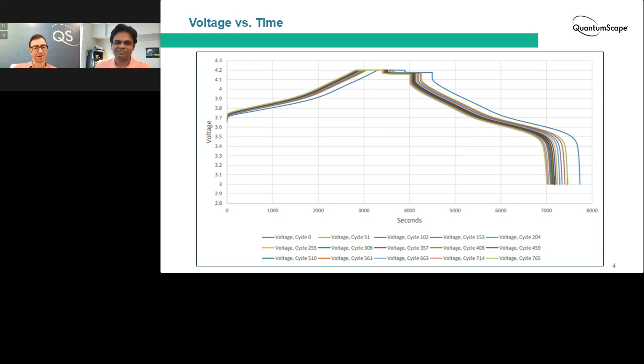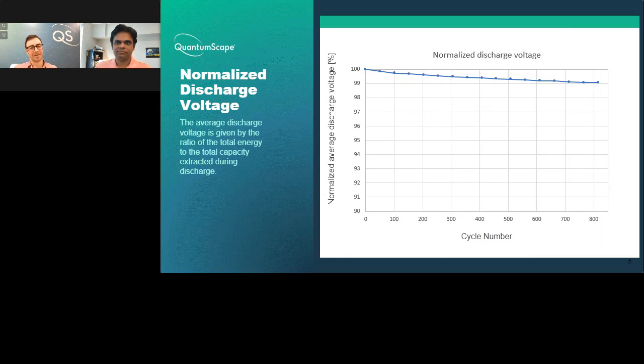So this is giving raw voltage versus time, but we can understand a little bit more from these curves if we do a bit of analysis. So on this next chart, what we're showing is the normalized discharge voltage across cycling. So what that means is you take the discharge voltage curve that we saw on the last slide, you take the average of the voltage, and then you compare how does that average voltage compare one cycle to the next. And so this is showing again for every 50 cycles throughout the test how that discharge voltage changes.